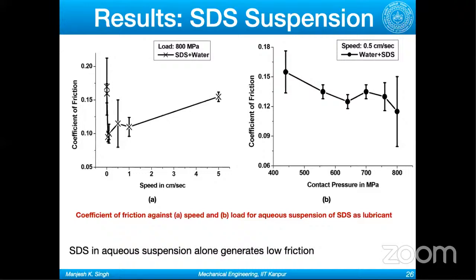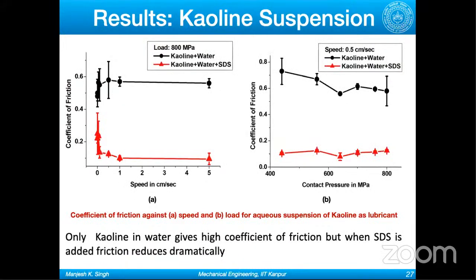So it could be that nanoclay is basically doing nothing. It's just the SDS which is forming a monolayer on the surface and reducing the friction in the case of the nanoclay plus SDS mixture or suspension in water. We again repeated the same experiment with kaolin plus water, and here also when we add SDS, we get lower friction. So we are not sure what the role of SDS is. The objective of adding a surfactant was to stabilize the emulsion. But as we saw in the previous slide, only SDS also gives us low friction.